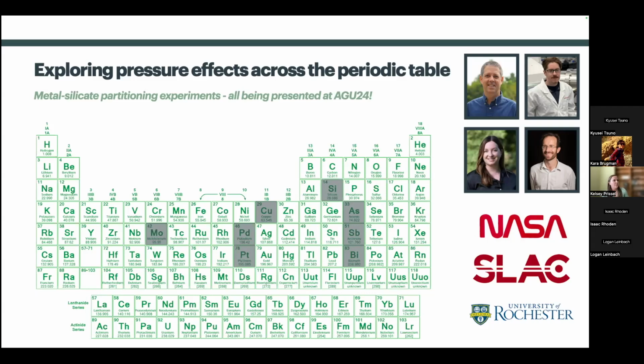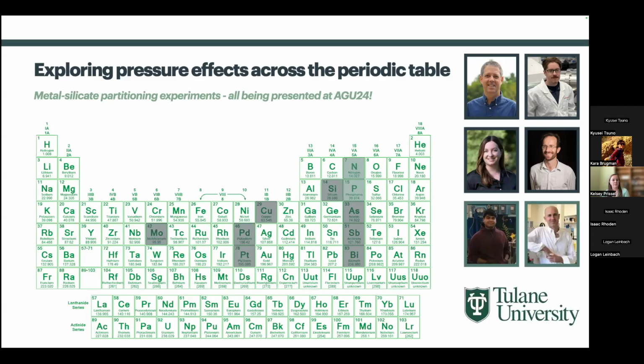We are getting a little bit more data. We have one last round of laser ablation data to get on our experiments, but then we're excited to put this result out into the journals. We're still scratching our heads as to why antimony and bismuth were the only 2 elements that had this pressure effect. But what's exciting is to continue across the periodic table and see if we find additional patterns. Another one of our collaborations is with our colleagues at Tulane University, where we're studying nitrogen and phosphorus. And similarly, we are finding effects of pressure for these elements.